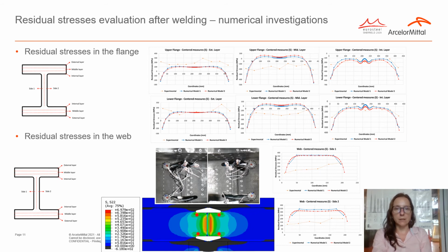In the web area, the output results of the numerical simulation show considerable differences up to 200 megapascal when compared with the experimental tests. After various examinations, the preliminary conclusions show that since the welding procedure is made in stages, the weld of flanges imposes a contraction of the beam in both directions before starting the weld of the web, which causes distortion in the web mesh area, and further investigation needs to be made.